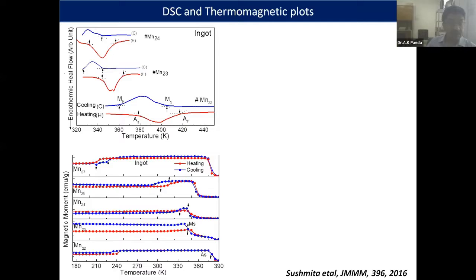And it shows very interesting properties. You see that when you go for manganese 22, it has a fairly high austenitic start temperature. This is the austenitic start temperature that has been put on the arrow, whatever we have got from the differential scanning calorimeter, just to indicate the position of the austenitic start. You see that it goes on decreasing. And then in the intermediate stage, we have austenite and martensite. And subsequently, when you go to very low temperature, you have the martensite occurring at a much lower temperature in the case of manganese 27. So that is also evident from the thermomagnetic plots.